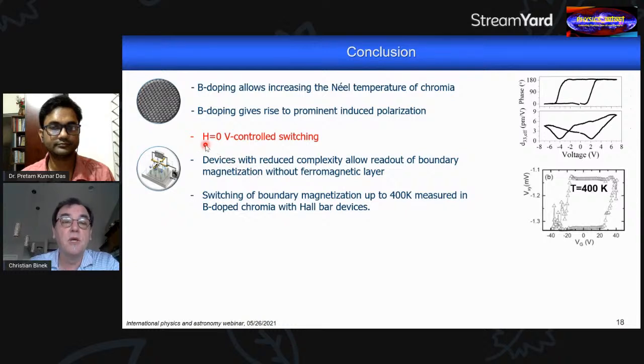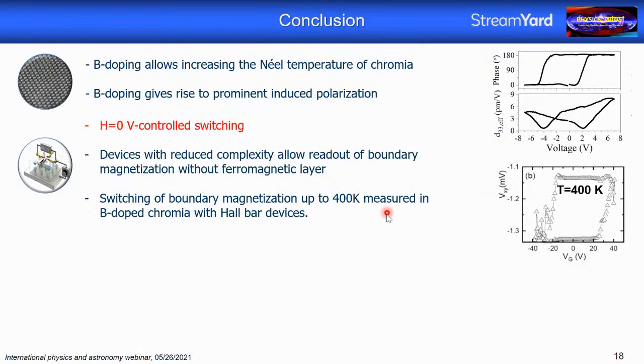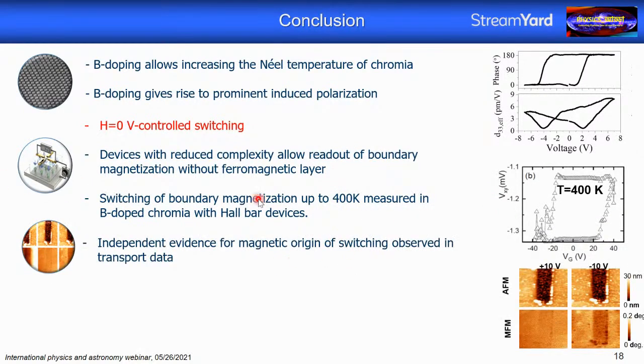And what is important, we can do that in zero magnetic field, and we can do that up to 400 Kelvin. So I haven't shown you these data, but this is a hysteresis loop taken at 400 Kelvin, so the effect is still present. I showed you some independent evidence that this switching is indeed a magnetic phenomenon and not an artifact.